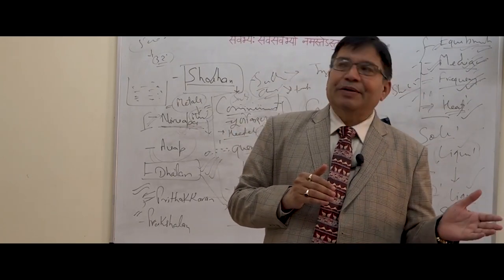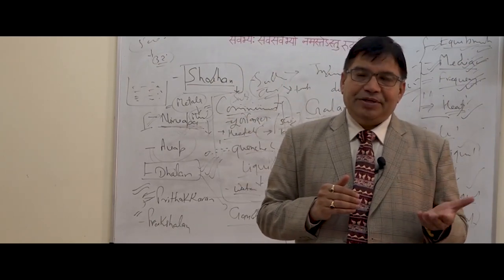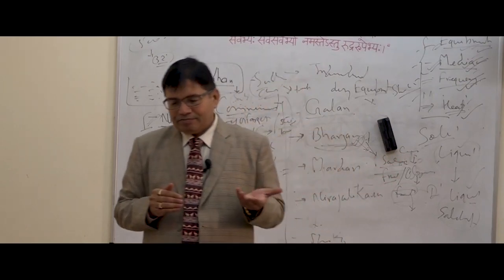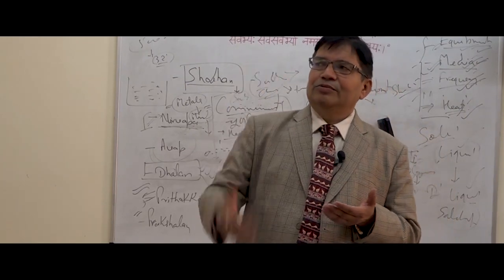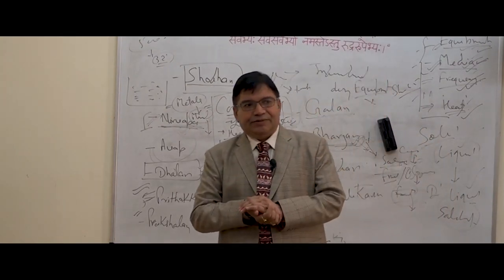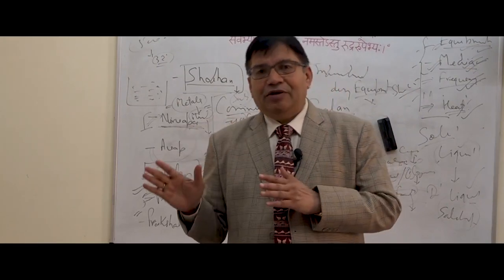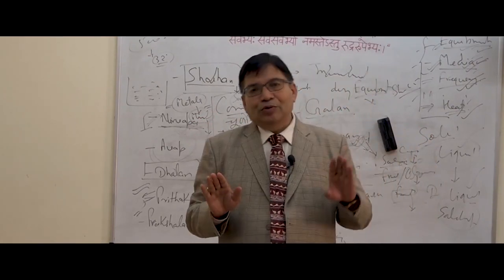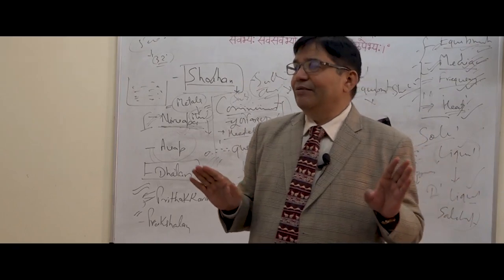An idea developed in the minds of some scientists: if the only purpose is the reduction in the particle size, and if the objective is a sudden change in temperature, then why are we using all these materials, Tila Taila, Takra, cow urine and the rest? One can use water only and get the particle size reduced. An experiment was planned here back in 1995-1996, in which the copper was quenched in plain water 35 times, and it was really reduced in particle size in the same way as with all the 5 liquid media quoted in the Ayurveda classics, and specifically our Rasa Shastra books.